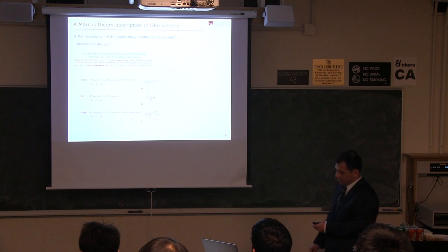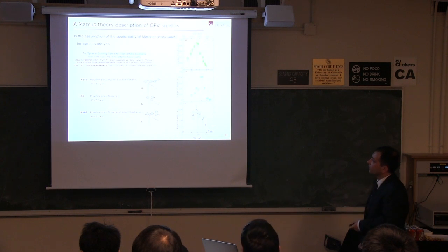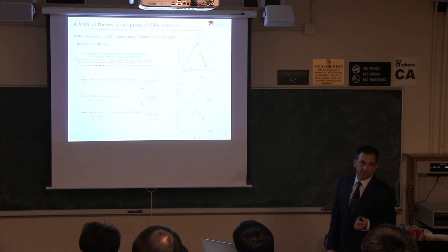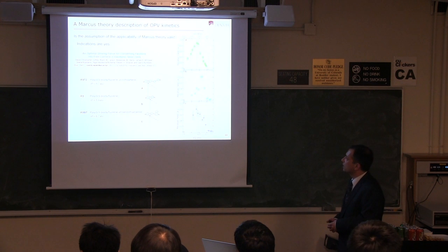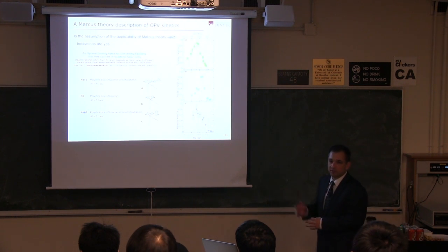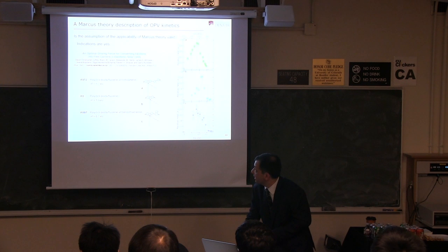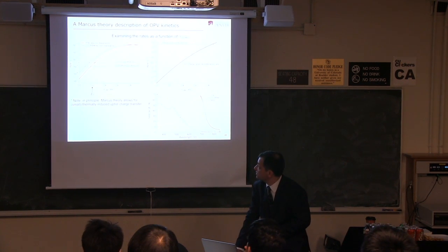Okay, so first of all, is Marcus theory valid? Do we get a parabolic shape to the rate constant? My colleagues at NREL have given a big hint to the answer, which is basically yes. What they did was take a series of polymers, combine them with a whole bunch of acceptors, and measure the charge transfer rate as a function of delta G, the band offset. Lo and behold, they do get upside down parabolas with a peak position that tells you what lambda is, the reorganization energy. So it tells you the theory works, at least qualitatively, and if you believe the numbers, the reorganization energy is about 0.5 electron volts in these materials. Very useful.